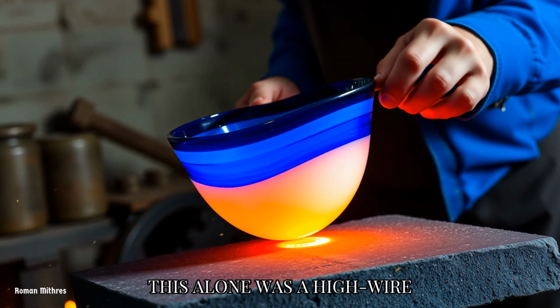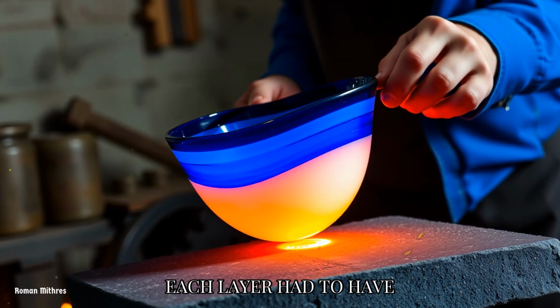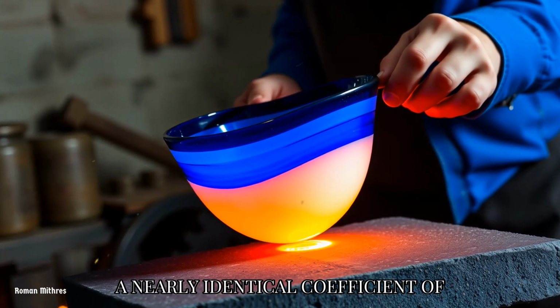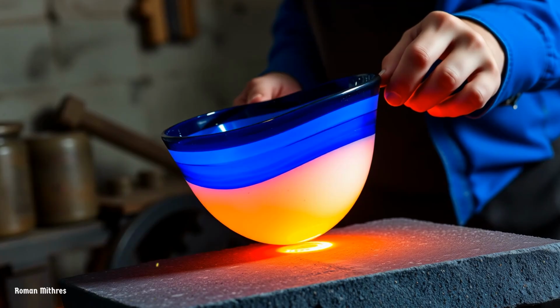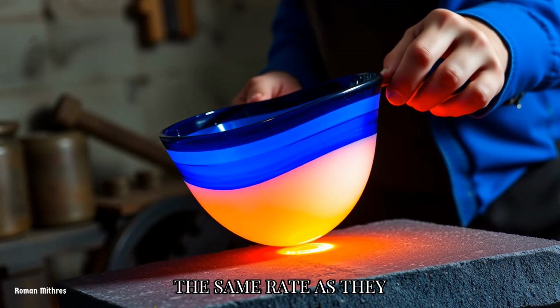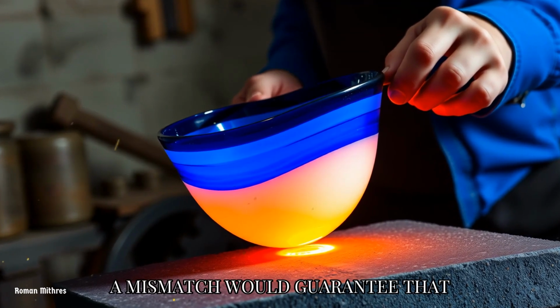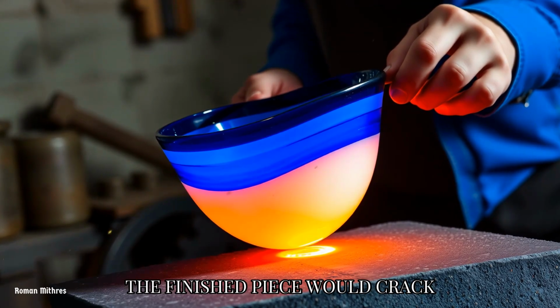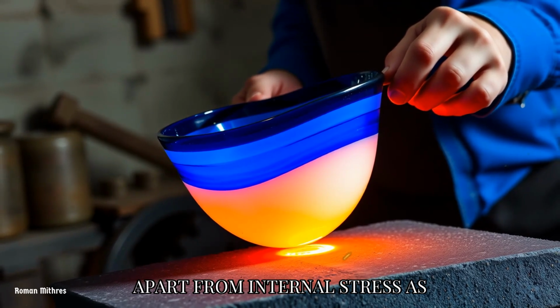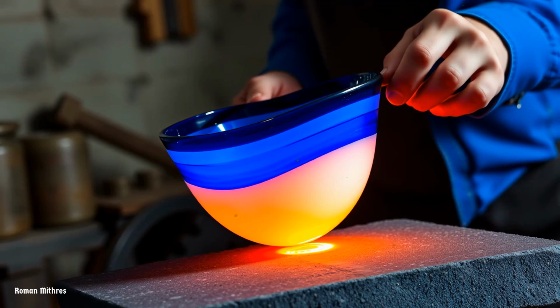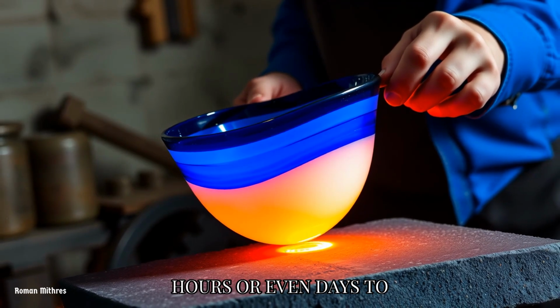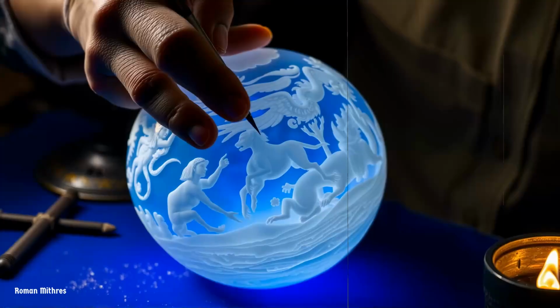This alone was a high-wire act. Each layer had to have a nearly identical coefficient of expansion. They had to shrink at the same rate as they cooled. A mismatch would guarantee that the finished piece would crack apart from internal stress as it cooled, a flaw that could take hours or even days to reveal itself.